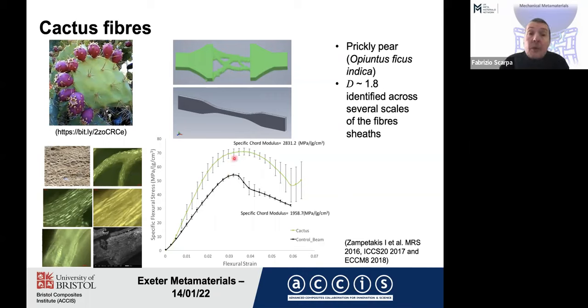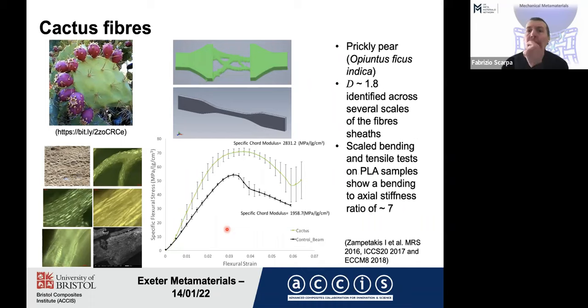And what we have observed was that those fibers, experimentally, the real ones but also the surrogate ones, do all show a ratio between bending stiffness and axial stiffness between 6 and 8, which is quite unusual in open literature, because a normal composite tends to have a ratio between bending stiffness and axial stiffness of about 1.2. In some three-dimensional wovens, you can start to have something higher, but those types of ratios are quite unusual. And you can also see these are experiments performed of three-point bending with the scaled dimensions.